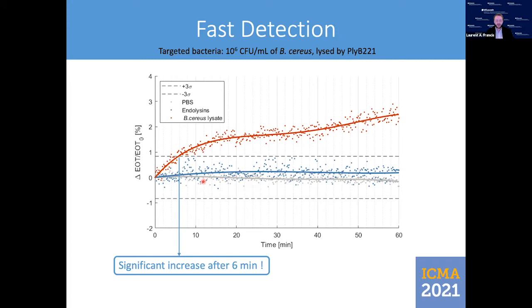The negative control using only endolysin, which is in blue here, can pass through the membrane and induces a slight increase of the relative effective optical thickness, indicating the passing through the layer, but nothing special can be observed in this case. This increase is, however, within the noise level, which is seen here, and which is calculated as 3 times sigma, the signal of the PBS solution.